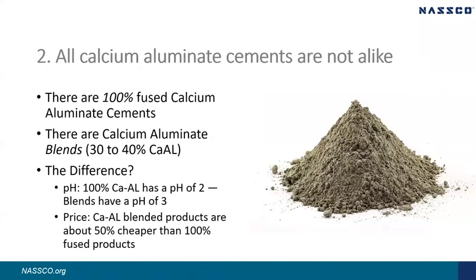My second point is that regarding calcium aluminate cements, please note that not all calcium aluminate cements are alike. There are 100% fused calcium aluminate cements where the cement and the aggregate are both calcium aluminate. And then there are calcium aluminate blends where the calcium aluminate is the cement, but the associated aggregates are less expensive materials. Performance-wise, the differences are 100% fused calcium aluminate performs down to a pH of 2, while the blended products perform down to a pH of around 3. If a design engineer does not specify, the contractor will choose the less expensive option, but the structure will not be as well protected in the more acidic environments.